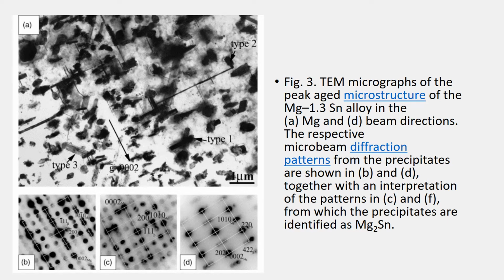This is Figure 3. Figure 3 illustrates a TEM micrograph of the peak age microstructure of the Mg-1.3Sn alloy in the magnesium and the beam directions. The respective microbeam diffraction patterns from the precipitates are shown in B and D, together with an interpretation of the patterns in C and F, from which the precipitates are identified as Mg2Sn.